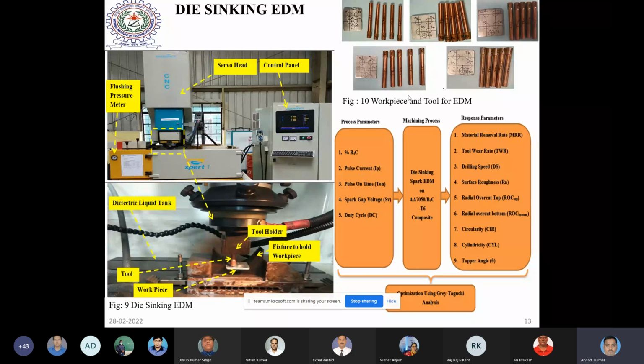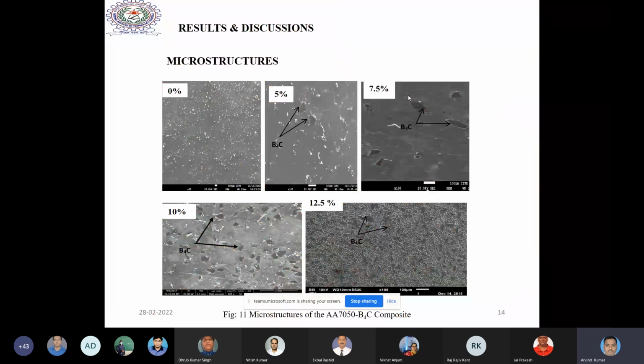So the major finding for this composite was, right from 0%, 5%, 7.5%, 10%, and 12.5%, I have seen that as I have increased the percentage of reinforcement, we have a uniform distribution of particles. This distribution shares the load coming on the composite, and hence the load bearing capacity increases. The major challenge of this kind of casting is the distribution of particles. If it is distributed, then it will show good properties. If it is not, then of course the composite will have bad properties.